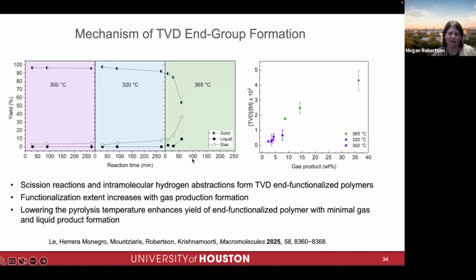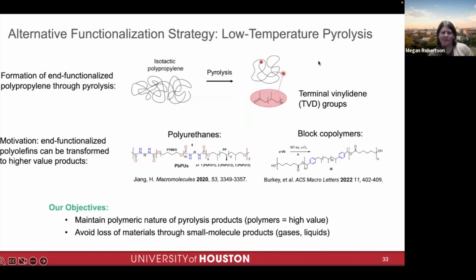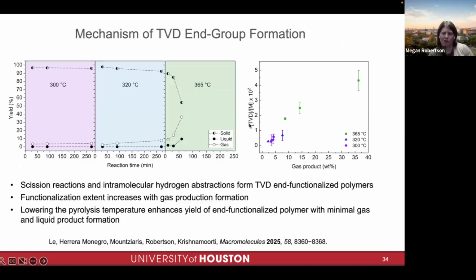Another way to look at this is, one thing I should point out, I forgot to mention: in this pyrolysis process, the chain is cleaving. And when it cleaves, what you end up with are these terminal vinylidene groups that I'm showing here. There should be one on each end of each chain. So we wanted to track the presence of those. What we found is that the more of those terminal functional groups we form, the more gas we're producing. Essentially, that gas is coming off from the process of chain scission, and that's the only reason we're getting a little bit of that gaseous product.